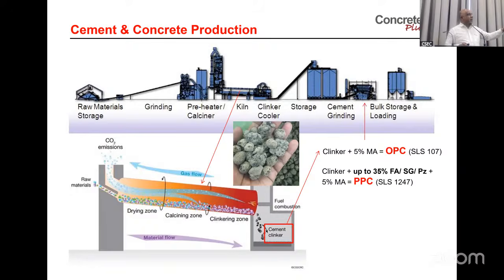So then the second type is PPC in Sri Lanka, which we call blended hydraulic cement. It can be fly ash, slag, or pozzolan. So here you can add up to 35%, either fly ash or slag or pozzolan. Only one material at a time. Third, in the limestone PLC, SLS 1253, you can add up to 20% limestone.